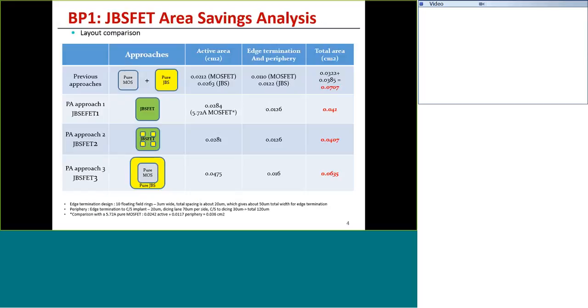So there are various ways in which you can do this integration, and then we can analyze the amount of area savings that we can achieve by this approach. Three of these are shown here, and so in what was done previously, there was a separate MOSFET and a separate JBS diode, and we can calculate out the area of these devices for a certain current rating, approximately 5 to 10 amps, and the area worked out to be 0.0707. The first approach, whose cross-section I showed you in the previous chart, we end up with a much smaller area of 0.041, so you can see a substantial savings.